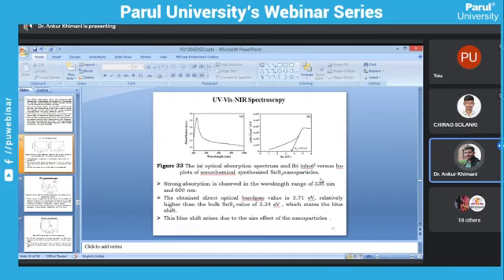So this is UV visible spectroscopy. Optical characterization is done through UV visible spectroscopy, in which we get the absorption versus wavelength graph. The graph is further studied to get the band gap of the material, and the (alpha h nu) squared versus h nu graph is plotted. The tangent shows the band gap of the nanoparticle comes out to be 3.71 electron volt.